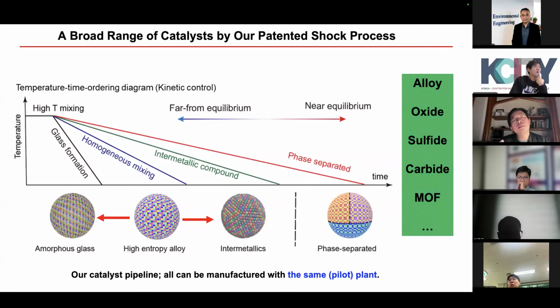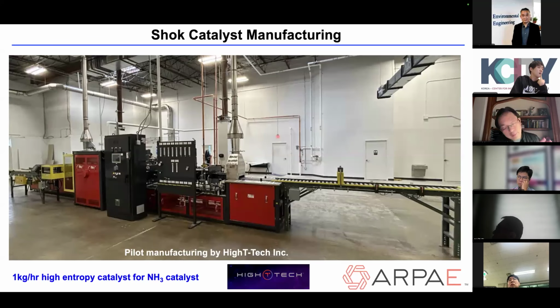And you can tailor the heating protocol. You can make an amorphous structure, you can make phase separated, you can make intermetallic. You play with this TTT diagram. Yeah. So just like a chef in the kitchen, you basically control the time and temperature, and you can get all kinds of compositions. I demonstrated alloy metal. You can also do oxide, sulfide, carbide, and even amorphous structure. So it's a platform. Once we identify one particular catalyst, we can use the same process, the same patented technology, to basically manufacture other catalysts for a whole broad range of catalytic applications. In this case, we're making 1 kilogram per hour of catalyst for ammonia oxidation applications.